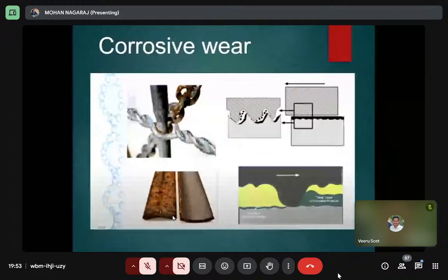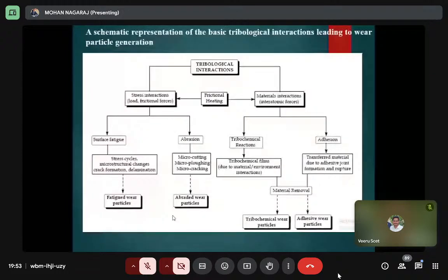This is known as corrosion. So this is a schematic representation of the basic tribological interactions related to wear generation. Tribological interactions involve load, friction and stress, surface fatigue and abrasion. Surface fatigue means cyclic stresses. Over a long period of time there is crack formation and the materials get damaged, with delamination due to fatigue, where micro and nanoparticles are worn out.